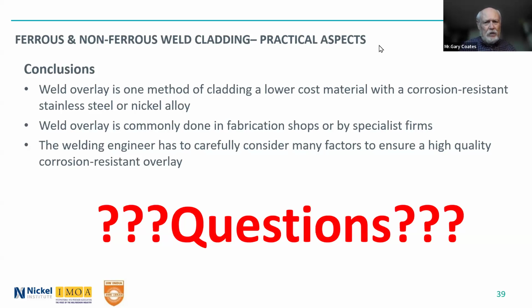For hot tapping in sour service, we cannot perform post-weld heat treatment, right, and use the tempered bead technique for welding. Do we recommend a stress corrosion cracking test to be conducted for sour service with 85 ppm hydrogen sulfide? I would hate to offer an opinion on that, to be honest. We are very concerned about stress corrosion cracking, and you'd really have to look at this. But yeah, when you're doing hot tapping, you can't do the post-weld heat treatment. You use the tempered bead. It's a very specialized technique that works most of the time. But I'm no expert on that, so I won't venture an opinion.